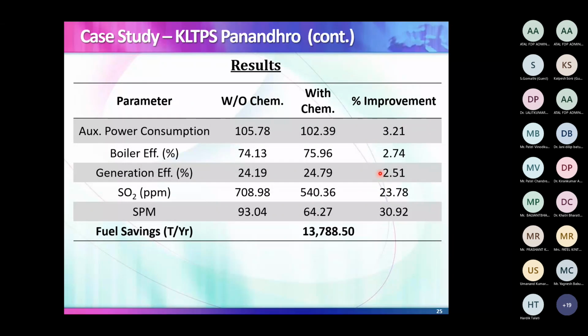Not this figure. At Ukai it was 34. Here it is 24 because lignite has a low calorific value and very typically high moisture. So that loss is much higher, stack loss. So this efficiency is less. SO2 reduction is 23.78% and SPM is 30.92%. So what is the fuel saving? 13,788.5 tons per year is the saving of fuel.